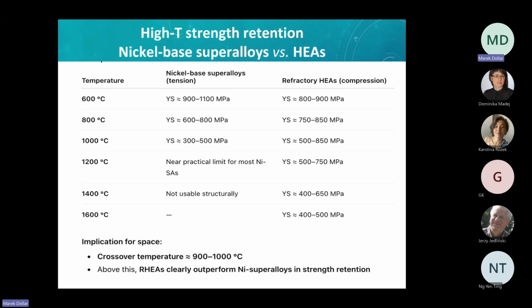I want to tell students that this is not a scientific number, but what we call usable strength is around 400 megapascals. So you can see that high refractory alloys are fine. This is again practical limit. This is as close as it gets to the melting temperature of nickel, which is, if I remember well, something like 1440, something like this. Even at 1600 degrees C, there is already evidence of high strength in some high entropy alloys.